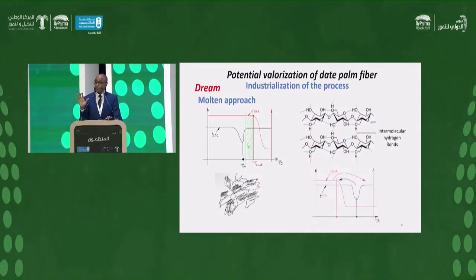In several works, we try to use natural fiber as reinforcement in thermoplastic composites using standard industrial techniques like extrusion or injection molding, and we can reach more than 20% of natural fibers to produce a composite by extrusion. But the problem is we still see the change of color, and we don't talk enough about that. That means we have the degradation of the natural fibers.